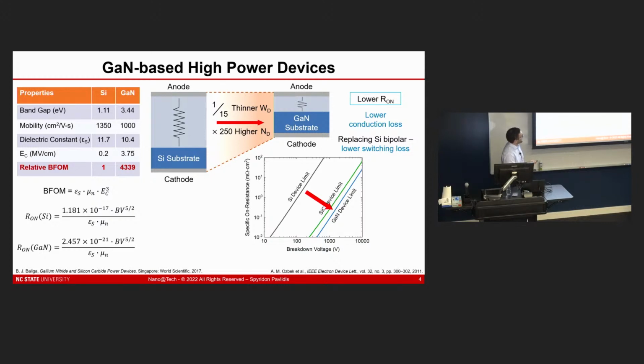Basically, we're able to draw a relationship between R-on and breakdown voltage for different technologies. When you work through different materials, you'll find different coefficients here, and then this breakdown voltage relationship with R-on with a power of 5/2 gives you the slope that you see, which is constant. But overall, what you're seeing is that you are shifting down to the bottom right-hand corner of this curve, and clearly, for the same breakdown voltage, a wider bandgap device is able to reduce your conduction losses. So this is really why GaN is exciting.